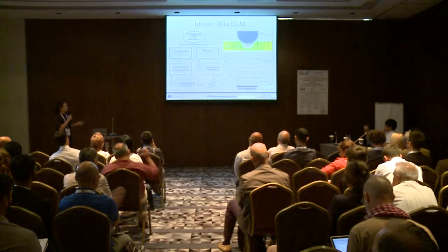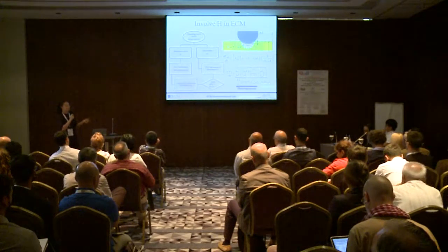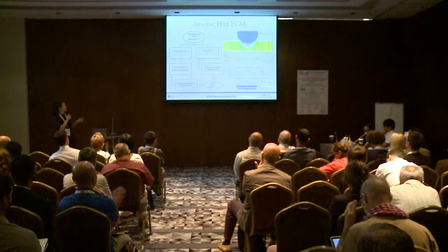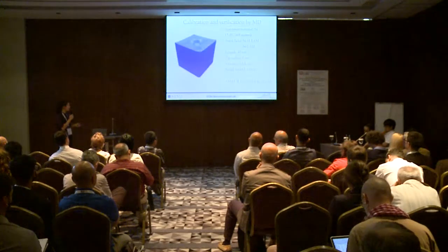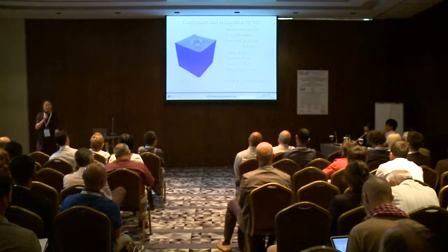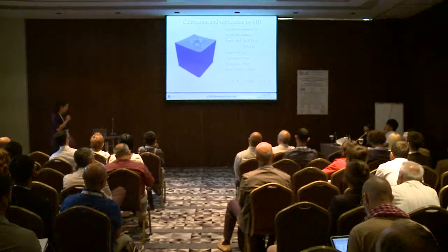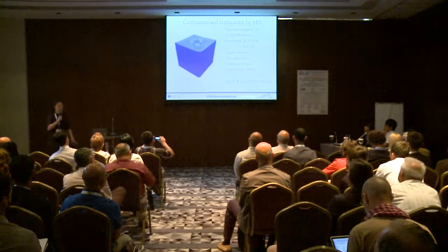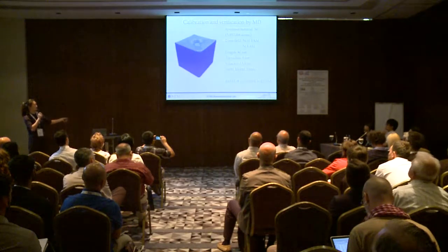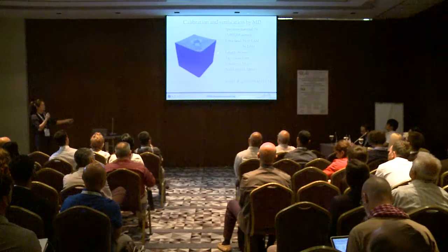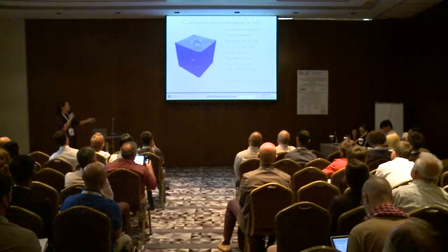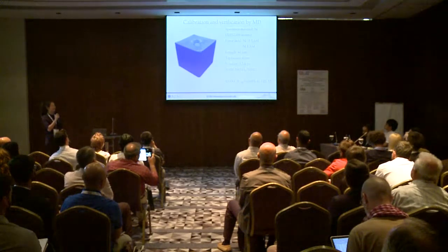So now we have a very crude continuum model based on the expanding cavity model, involving the hydrogen there. Next, at the same time, we run molecular dynamics simulations to calibrate and verify this continuum model. Our simulation detail is that we have a nickel box of around 6 million atoms, and we use the nickel-hydrogen EAM potential and nickel EAM potential to describe the interatomic interactions.